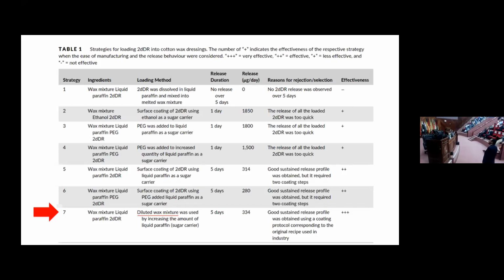So what we have found was that by just diluting the wax mixture by increasing the liquid paraffin, we were able to get this release over 5 days, and within the right dose. What is the right dose? By using extensive cellular studies and chem assays, what we have found is that if we apply 250 microgram to 500 microgram, that is the effective concentration of this 2-deoxy-D-ribose. So we were able to achieve this concentration from this formulation.